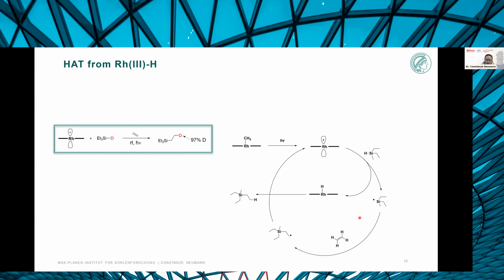And the catalytic cycle in the presence of light is then concluded by the hydrogen that was positioned on the rhodium center in the first step of the reaction getting picked up again by the carbon-centered radical in order to close the catalytic cycle and reform the rhodium-2 catalyst, which was crucial to us because that is a mechanism that is also viable for a transformation that can proceed in the absence of light, which we observed experimentally.